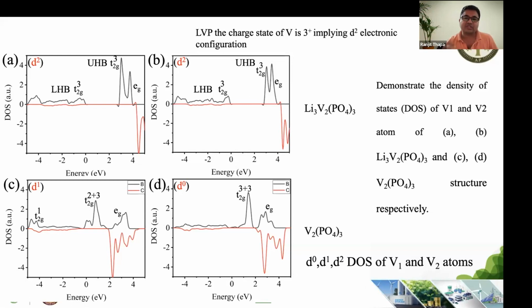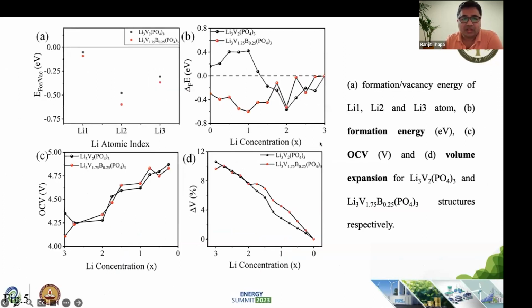So that means lithiums have some roles, oxygen has also some role, vanadium also has some role, that we have to understand and address to the experimentalist very clearly, what they should do. Then when we have done it that way, what we found out, you can see that lithium 1, lithium 2, and lithium 3, the formation energy per vacancy is different for different lithium. So that means if I change this formation energy, if when I'm bringing out one lithium, I need more energy for one lithium, I need less energy for another lithium.